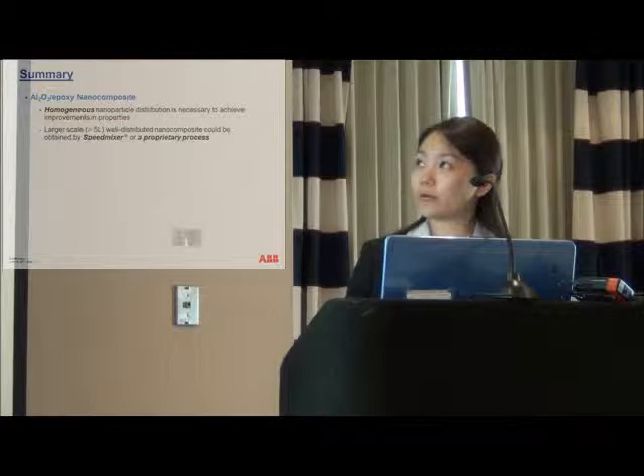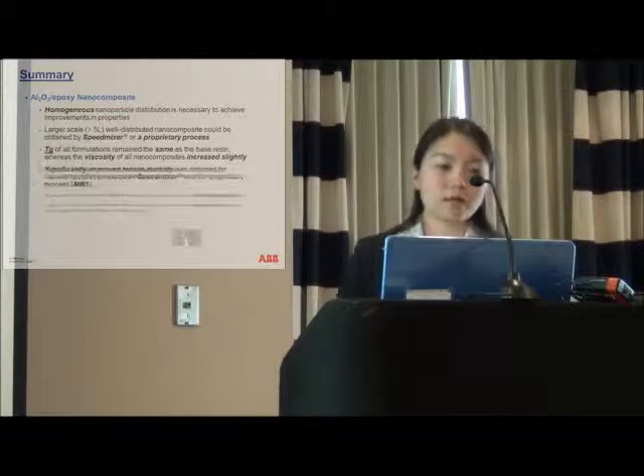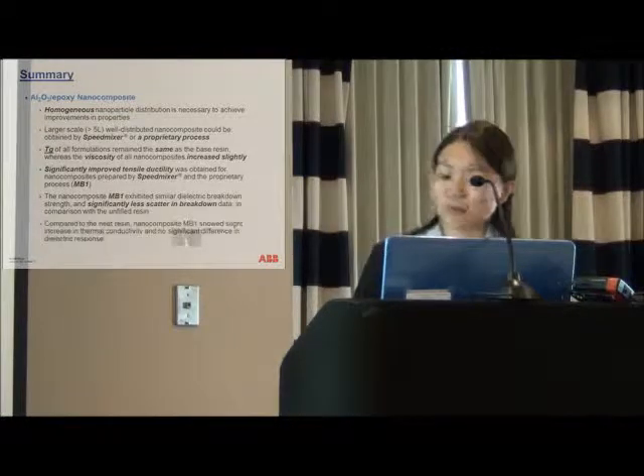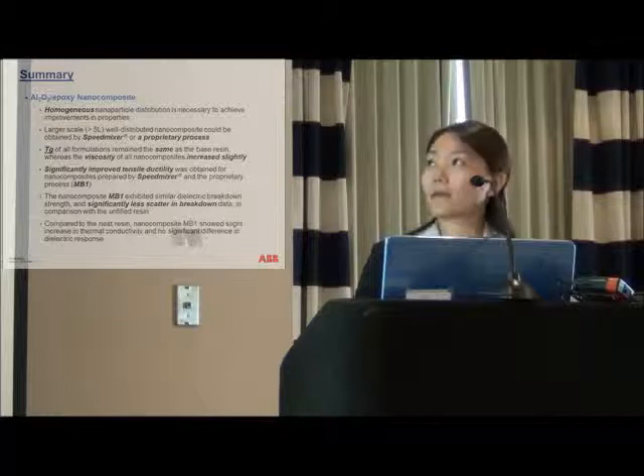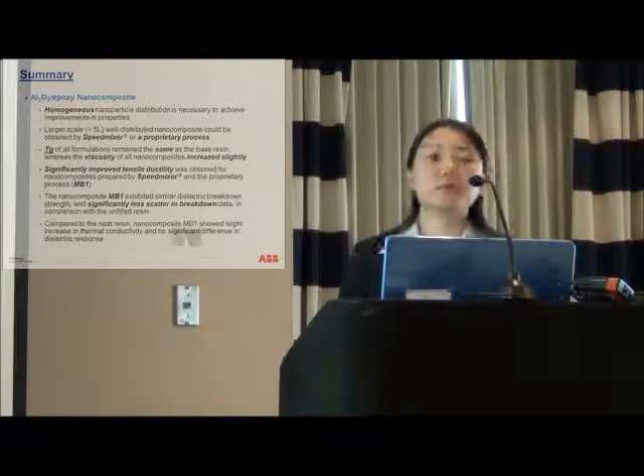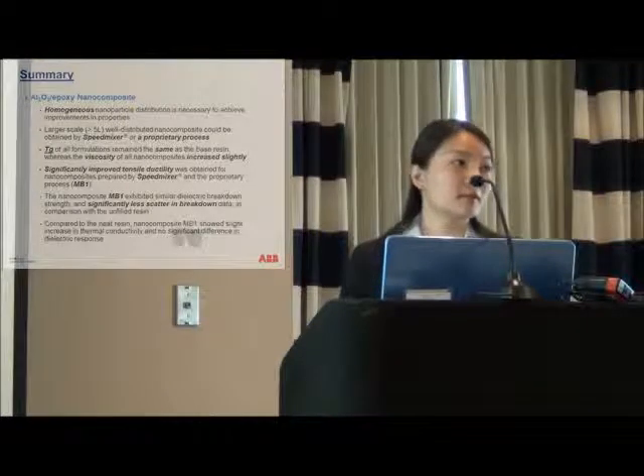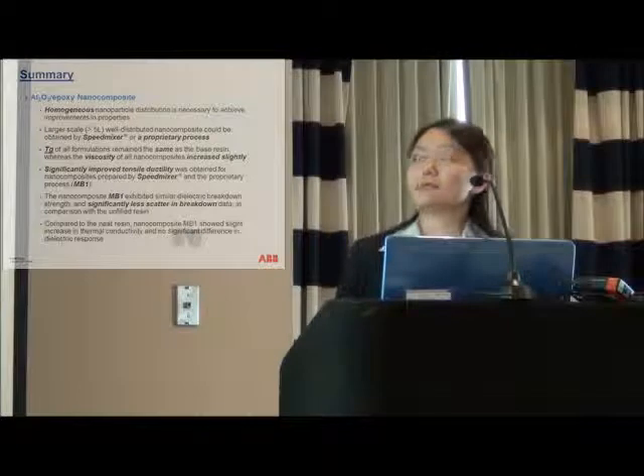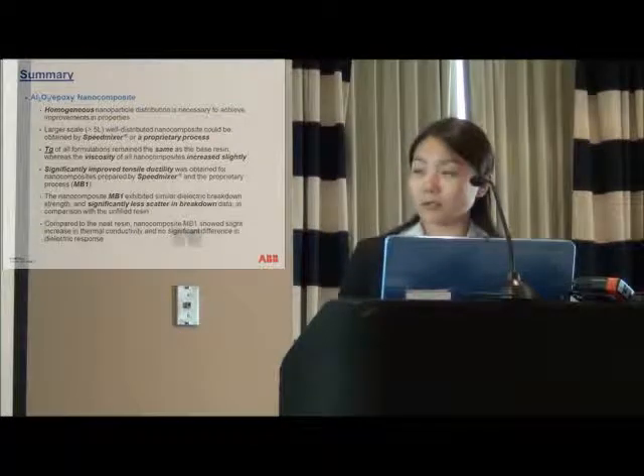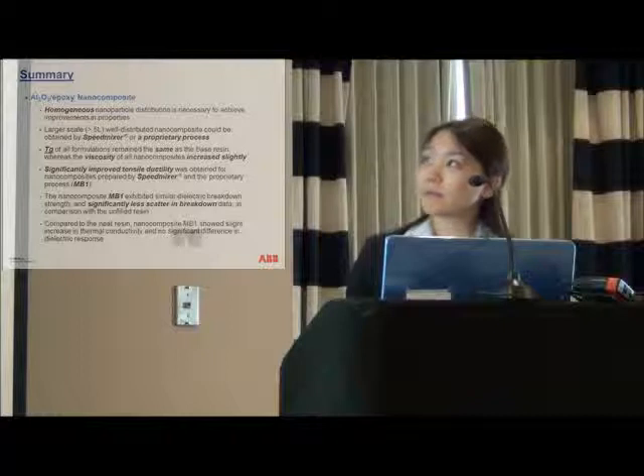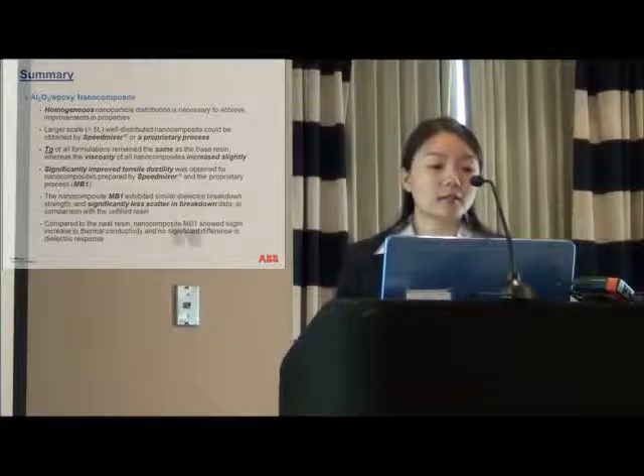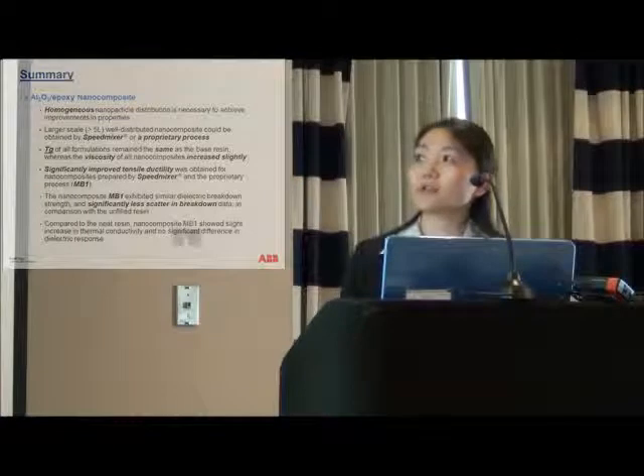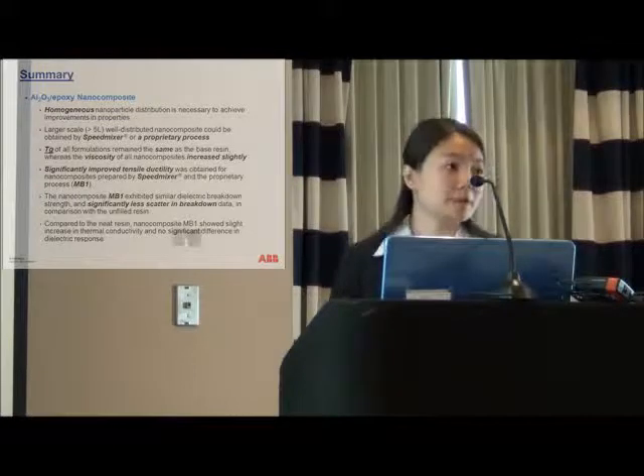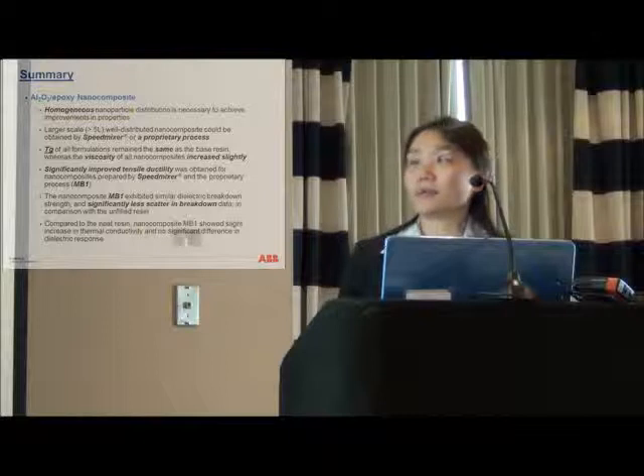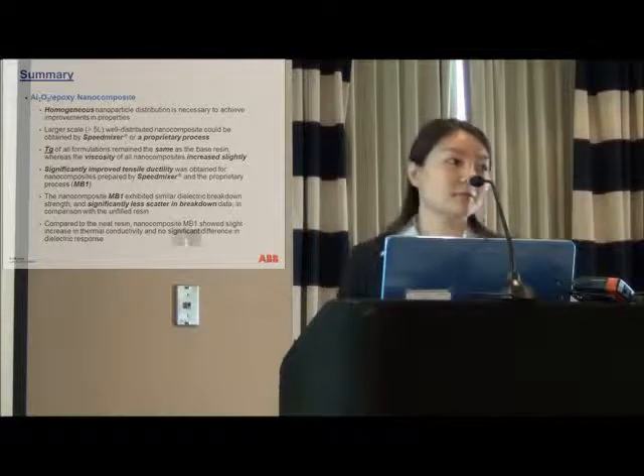So, the summary of my talk: we tried to upscale this alumina filled nanocomposite, and we noticed that homogeneous nanoparticle distribution is really critical to achieve any improvement in the properties of the nanocomposite. And a large scale, well distributed nanocomposite could be achieved by using a speed mixer, or the master batch 1, though we don't know how they really did it.